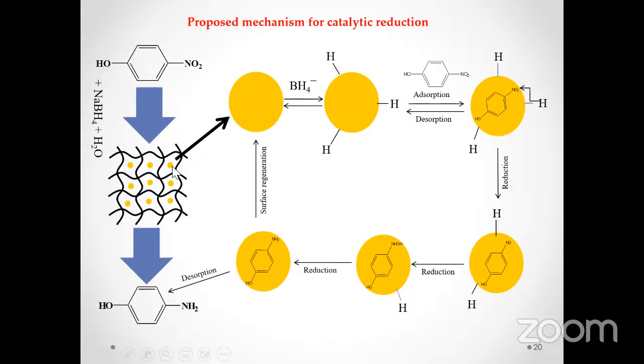Initially, the borohydride and the reactant, which is nitrophenol, are both adsorbed at the surface of the catalyst, as shown in this diagram. First borohydride is adsorbed on the surface of the catalyst, and then adsorption of the nitrophenol takes place, and then stepwise reduction of the nitrophenol occurs, and finally when the product is formed, that product is desorbed, and this catalyst becomes available for its catalytic role again, and the same cycle is repeated again and again in the reaction medium.